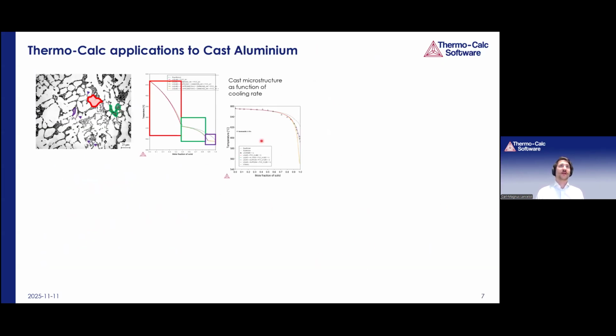So for cast aluminum alloys, of course, we want to be able to simulate the cast microstructure, and we can do that easily using the Scheil-Gulliver equations in the Scheil calculations. We can simulate the cast microstructure. We have some dendrites, we have some eutectics, and we have some intermetallic compounds forming, including the segregation profile during the growth of these dendrites as a function of cooling rate.